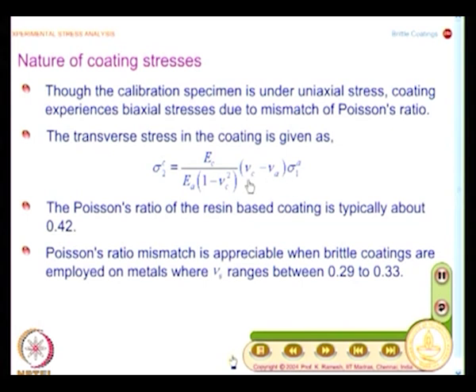So, the Poisson ratio mismatch becomes important in brittle coating analysis. And what is the Poisson ratio of the resin based coating? It is typically about 0.42. And the Poisson ratio mismatch is appreciable when brittle coatings are employed on metals, where nu s ranges between 0.29 to 0.33. So, this is what you have to keep in mind.